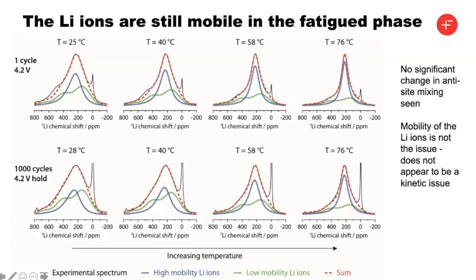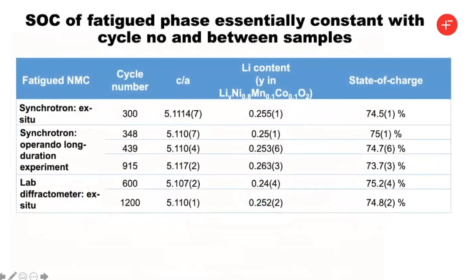So we then asked the question, is there something about, say, the anti-site mixing or the disorder that's changing the lithium mobility? And so you've seen these lithium mobility experiments before for the first cycle, where we could model the spectrum as a function of temperature. So remember, we see as you go up in temperature, the lines collapse, which is indicative of lithium mobility. And we can compare the first cycle with the sample after 1,000 cycles. And you can see, while there is some increase of disorder, the lithium ions are still mobile at 4.2 volts. So it's not that the lithium ions are trapped because of the mobility per se.